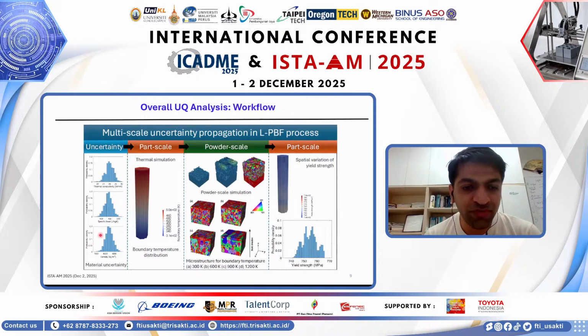So we have specific heat capacity, density of the material, and thermal conductivity, which are the three material properties that we are varying. And then we will look at the impact of this on the thermal simulations at the part scale. And then we will export the boundary temperature distribution from this simulation here. And this boundary temperature will then be an input to simulate how the powder bed fusion process works, how the melt pool is generated, how the solidification happens, how the grain growth happens, and so on. And for different temperatures, we will have these kinds of microstructures. And these microstructures will then be used to estimate the yield strength of the material and the distribution of the yield strength of the material as well.